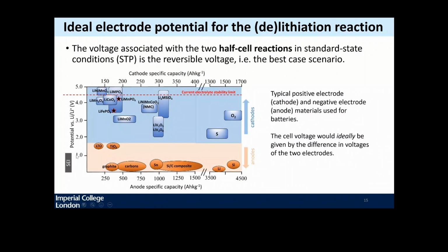are stable there. The same here, you may see that I put here an SEI layer. This means that all of these materials, when chosen for negative electrode, lead to a degradation that occurs as a result of an undesired electrochemical reaction, and so on. So there's quite a lot you can do just based on the Nernst potential, but this is, of course, a very small part of the picture because we've assumed thermodynamic equilibrium.